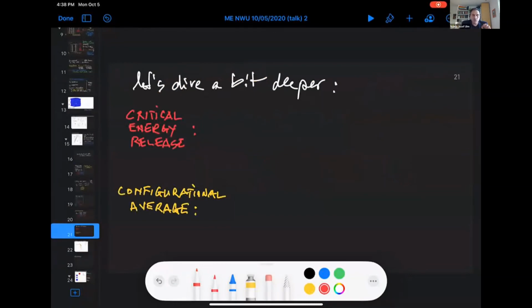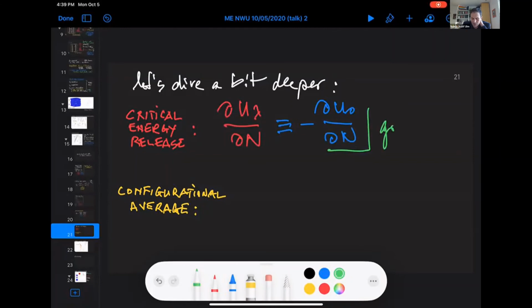Well, at this critical state, we basically have a full Griffith type criterion: that the energy dU_lambda over dN is equal to minus dU_0 over dN. So let's be clear about this: this is the ground state energy, and the other side is the strain energy release, right? Then this is nothing else but Griffith. Basically, the energy release rate and the fracture energy on the right-hand side, the critical state.